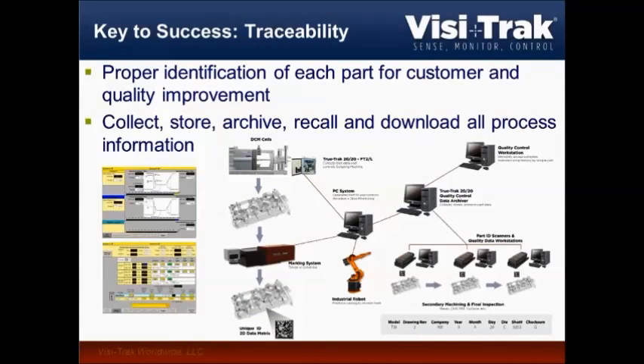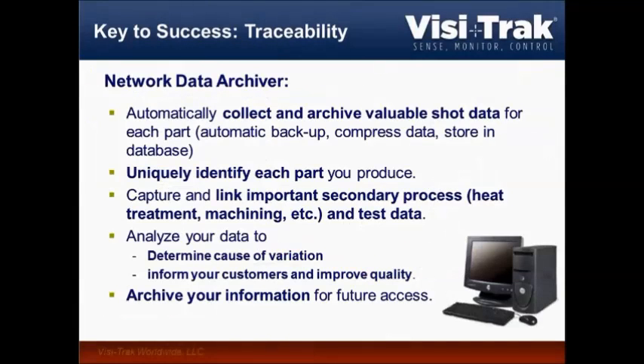And then we had it before, a proper identification of each part when it comes out is important. You can very often see this now on all the structural parts for sure. So it's engraved on every part when the part comes out of the die casting machine, and then the barcode is scanned again for every subsequent process step. So you scan it before you put it into the heat treatment furnace, and then the heat treatment temperature curve is simply added into the data archiver, and anyone who later on scans the 2D code will see all the process parameters through the entire value chain. So this network data archiver is very important. It collects and archives all the data, and then helps to uniquely identify each part.